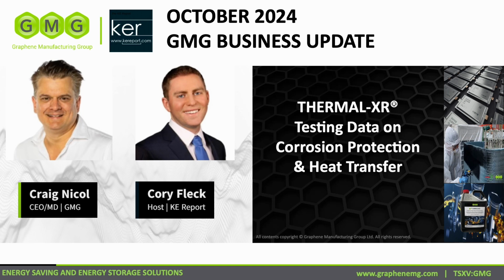We think there's two things it's doing. One is the graphene is providing an air gap inside the epoxy acrylic coating we have, and that graphene air gap means that there's no way for the air to get in to create the corrosion. But also the graphene that we use, as you guys know, is similar to the graphene we use in our battery. So it's creating a capacitor type resistance to corrosion, and therefore we think that it should have an even longer life than normal barrier coatings, because it's counteracting the corrosion which comes from the cathodic reaction from metal to air and water surface.